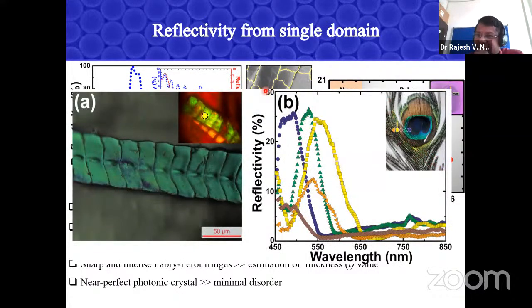With that, we also wanted to look at whether the peacock feather can be imaged in our setup. If you take a single barbule of the peacock feather, you can see this live measurement picture we took from our lab. You can see the laser is focused here, and I took different types of peacock feather. We can see that it shows different resonances, different reflectivity bands. When you overlay all these things, you see very nice colorations. That's what you see in those systems. We started with it as fun at that time, but now it has become a very serious activity in our group. A couple of students are working on this kind of biophotonic structures, or biogenic photonic samples.